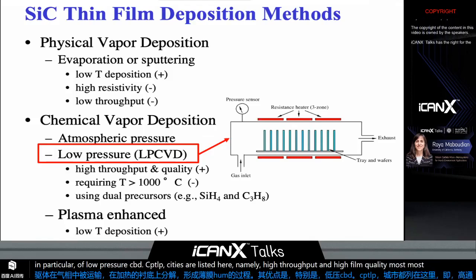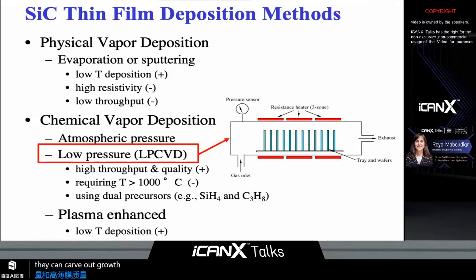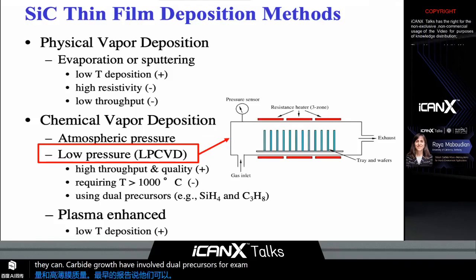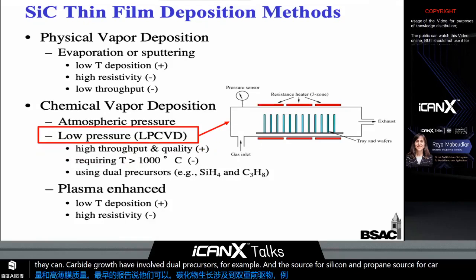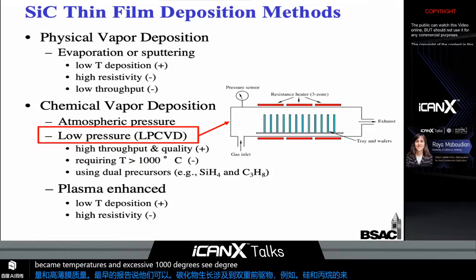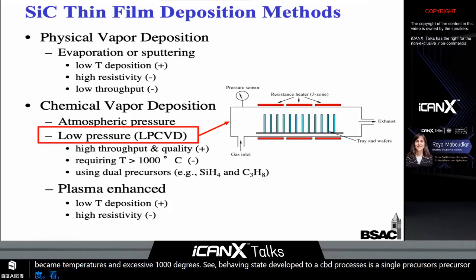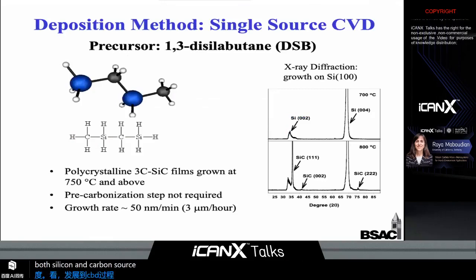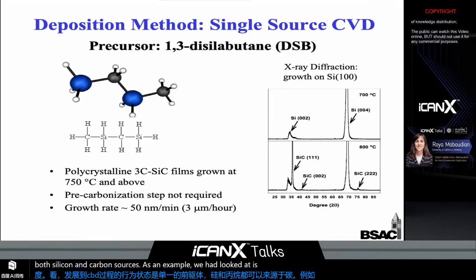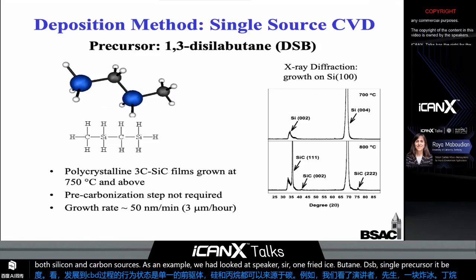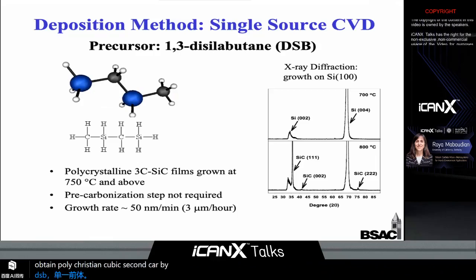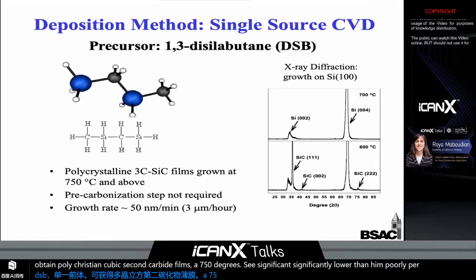Most earlier reports on silicon carbide growth have involved dual precursors. For example, silane as a source for silicon and propane as a source for carbon, requiring temperatures in excess of 1,000 degrees C. We have instead developed CVD processes based on single precursors, which carry both silicon and carbon sources. As an example, we have looked at this precursor, 1,3-disilabutane, DSB single precursor. We've been able to obtain polycrystalline cubic silicon carbide films at 750 degrees C, significantly lower than reported previously for silicon carbide growth.